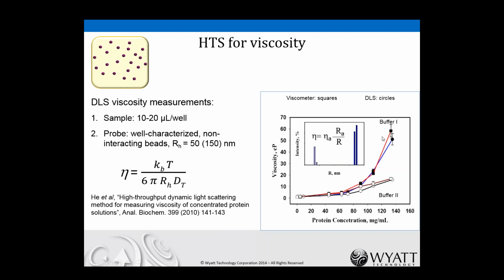So, I would not put this forth as the absolute best way to measure viscosity, but if you need to use very little sample, just 10 or 20 microliters of sample per measurement, and do it rapidly, and perhaps at the same time assess some other properties of the solution, they can just be loaded into the plate reader, and the measurement is done very quickly.